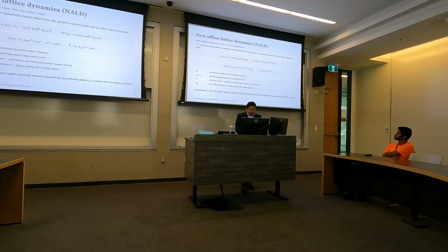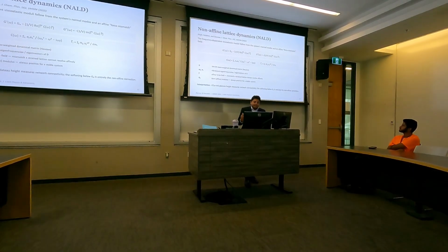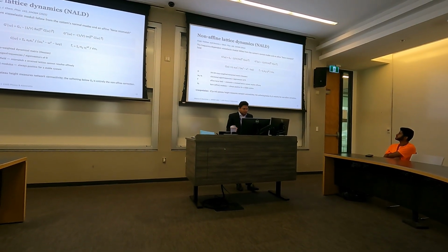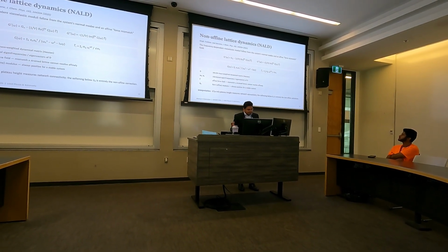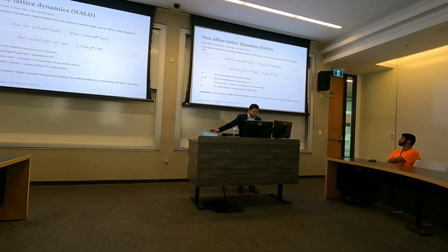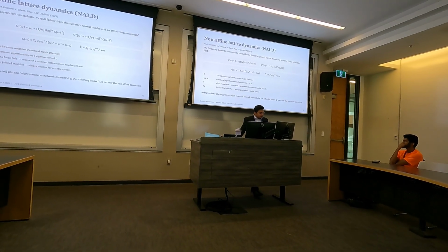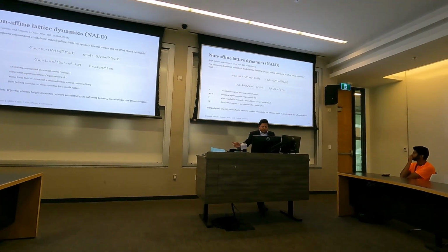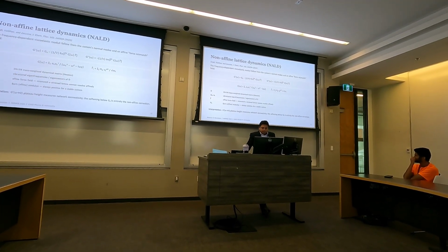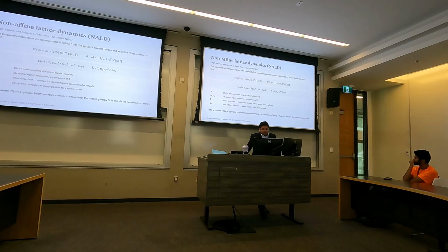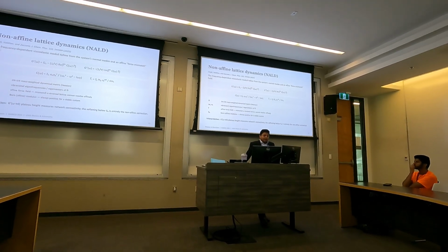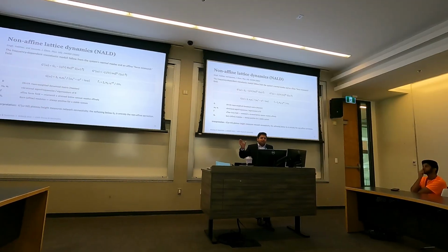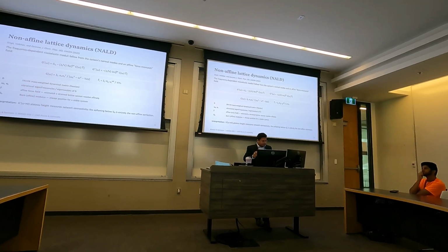The key ingredients are basically the mass-weighted Hessian matrix of the potential energy with respect to the displacement, which also gives us the eigenvalues for the vibrational frequency. And C of omega that you see here is a propagator built from these particular modes. The gamma tilde is the affine force field, which captures exactly the amount the force on each atom changes under the affine strain.